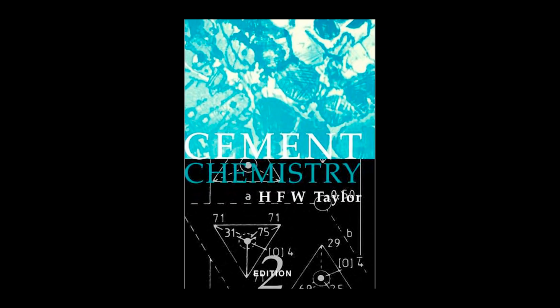These standards aren't just arbitrary guidelines. They impose strict compositional limits, and I think understanding why those limits exist is probably the quickest path to understanding durability engineering. The limits are there because if you exceed certain percentages, you are literally building a delayed structural failure into the cement from day one. That's it. What's the biggest culprit on that trouble list? Well, there are two phases that react far too slowly, and they're the big ones to watch. Magnesium oxide, MgO, and free lime, which is unreacted CaO. The content of MgO is usually restricted to a 4 to 5% maximum.